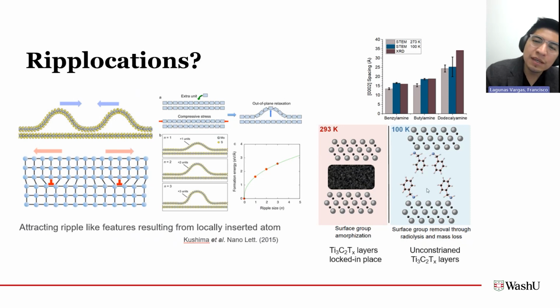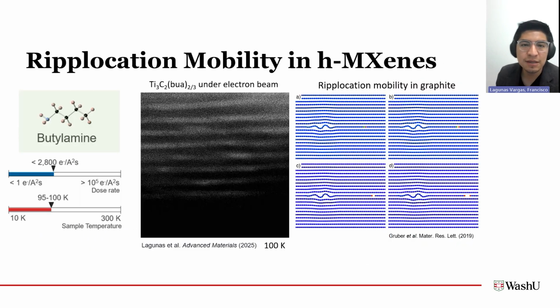So why were we not observing these at room temperature? Well, as you can imagine, you have these layers of your 2D material separated by organic surface groups. And as I showed, at room temperature we are amorphizing the surface group and in effect locking in the MXene layers. Whereas at liquid nitrogen temperatures, once we start degrading the organic surface group, we can start introducing different strain in the material that will then lead to the formation of these different types of Ripplocations.